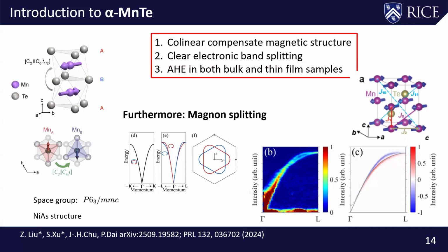The reason this is exceedingly strange is that, as I mentioned earlier, in the case of a simple collinear antiferromagnet, you should expect your spin wave bands, left-turning and right-turning, to be completely degenerate. Because in the case of a spin wave band, the entire magnetic exchange interaction is due to a so-called dipolar interaction, and dipolar interaction depends strictly only on the distance. It doesn't care what the local environment is, which completely contradicts naive thinking of an altermagnet. But in this case, the reason you have this spin wave band splitting is that the magnetic exchange coupling along the diagonal direction between this spin and this spin, which is J10, the 10th nearest neighbor, and J11 is actually different.